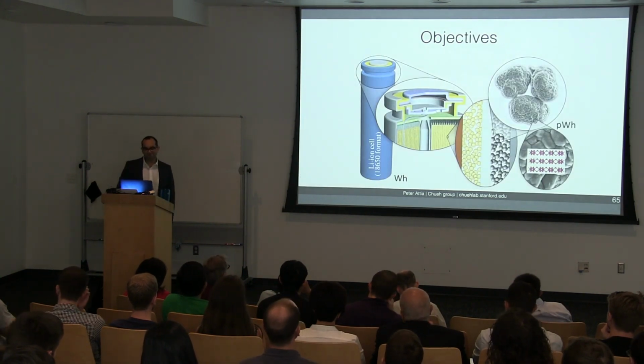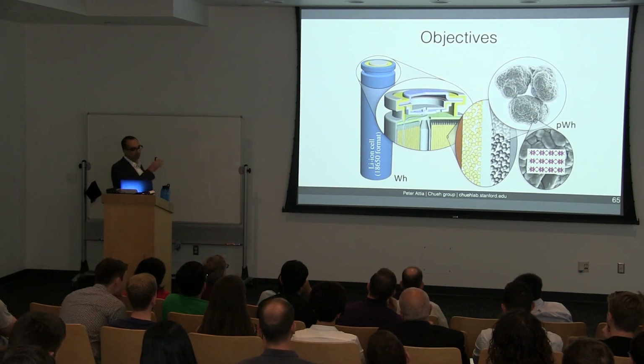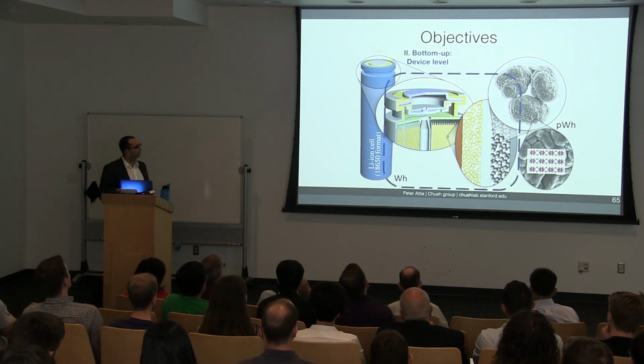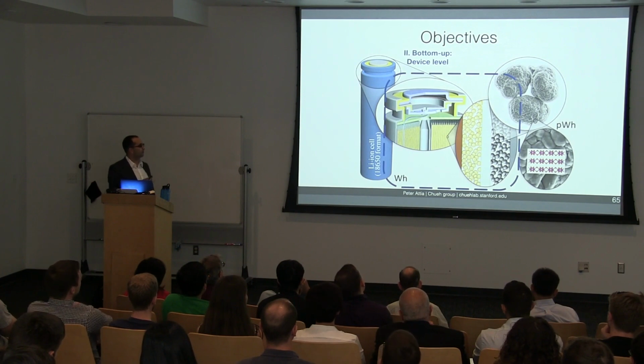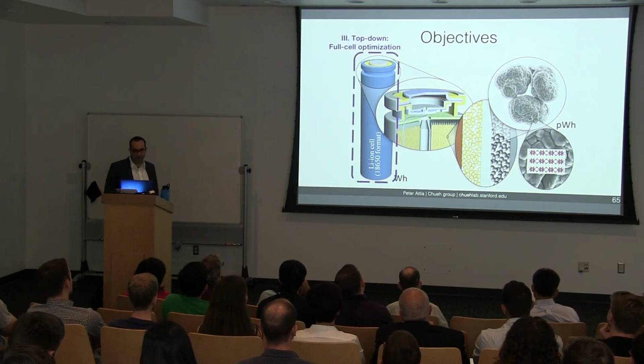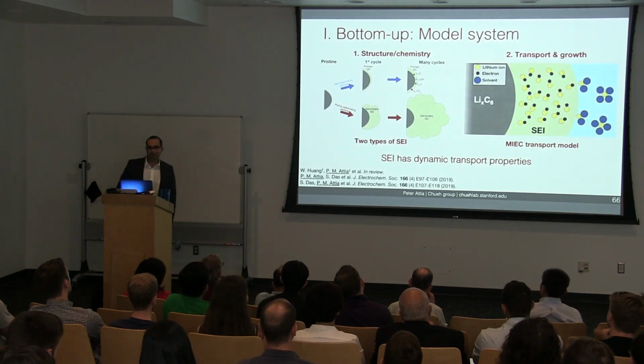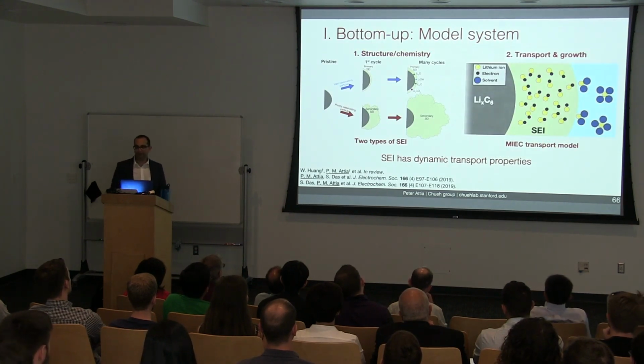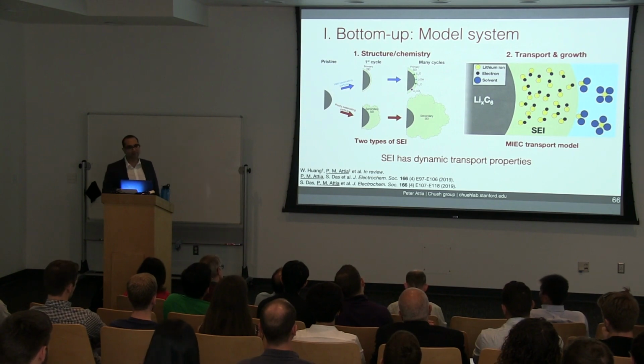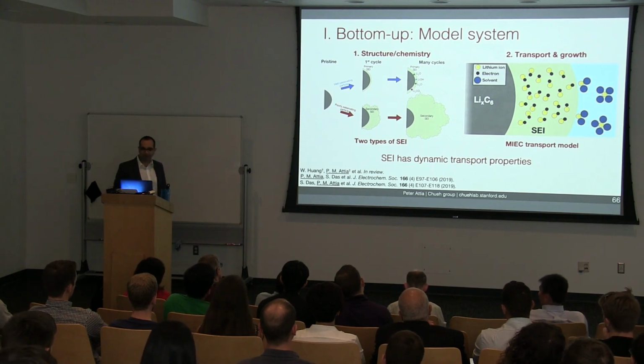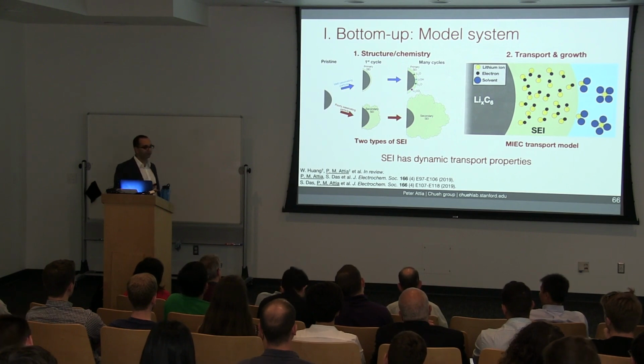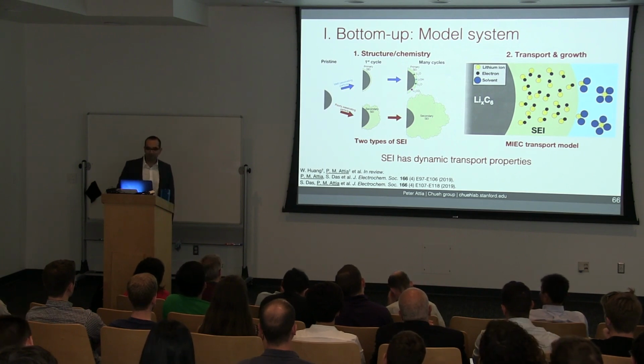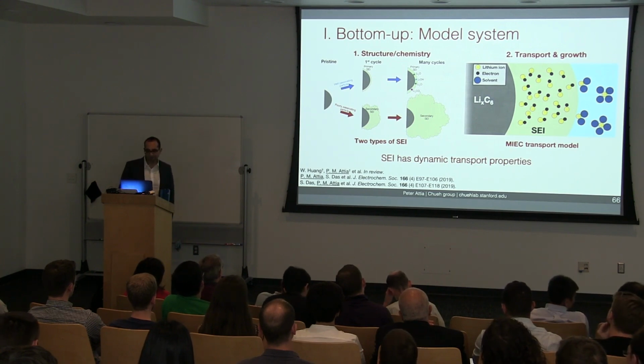So zooming out a bit, our original objectives were bottom-up approaches in part 1, device level bottom-up approaches in part 2, and the top-down optimization method in part 3. In part 1, we characterized the structure, chemistry, transport, and growth of the SEI using cryo-EM and electrochemistry. We found this really surprising result that SEI growth is much faster during lithiation than delithiation. Using this key insight, we built a model that captures the dynamic transport properties of the SEI.